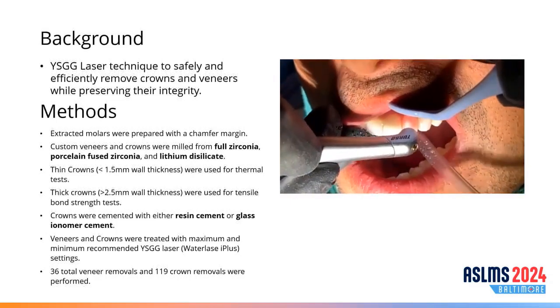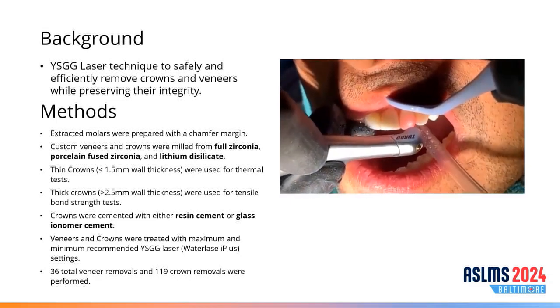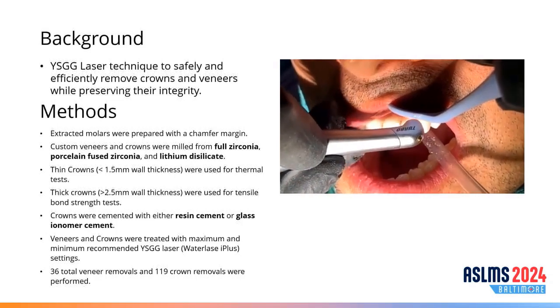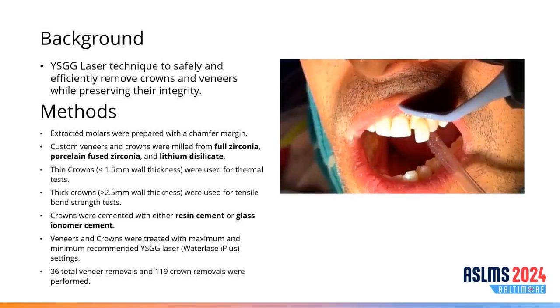Erbium lasers could be used to quickly and safely remove veneers and crown restorations. For this study, we used a range of materials. Basically, this would be effective on anything other than metal restorations. We used full zirconia, porcelain-fused zirconia, and lithium disilicate veneers and crowns. For cements, we used resin and glass ionomer cements. This would also be effective on RMGI cements.